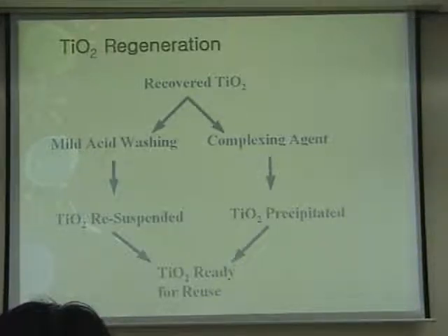here. And this is exactly the opposite here. The TiO2 particle is settled down here, while the complex ion material is suspended in the water, which can be decanted, and so we can get the regenerated TiO2. This regenerated TiO2 can be readily reused in the advanced oxidation process. The preliminary testing shows that the efficiency of this regenerated TiO2 was comparable to the brand new TiO2 particle. So it was very successful.